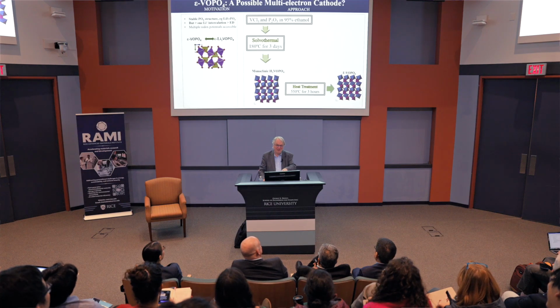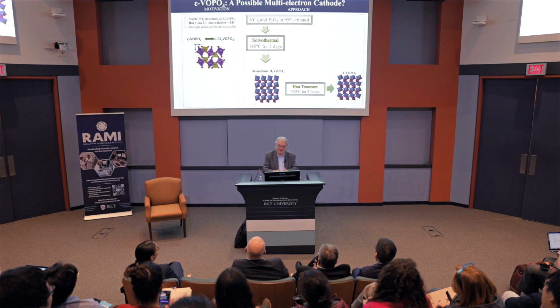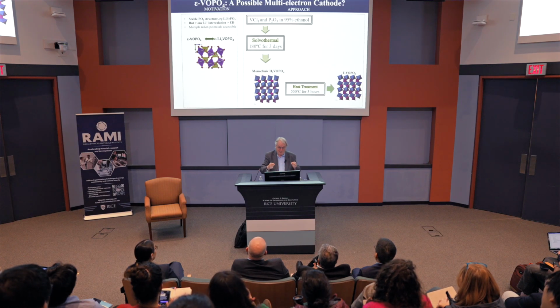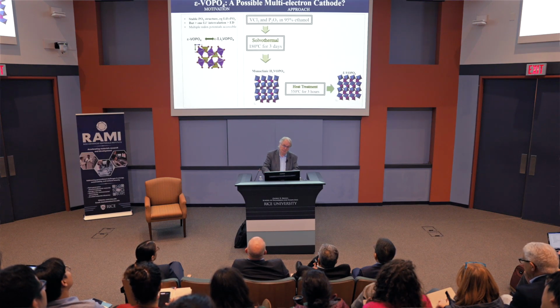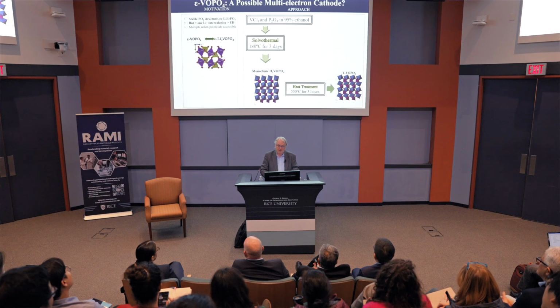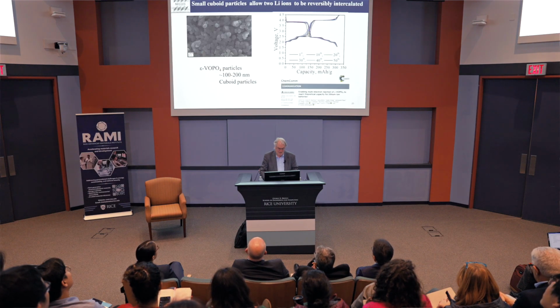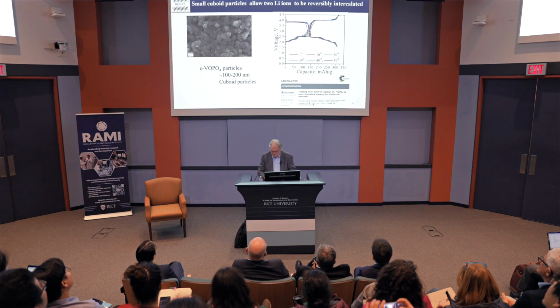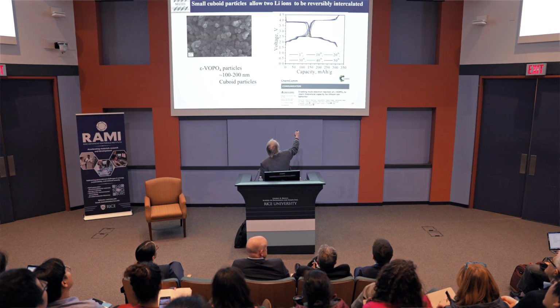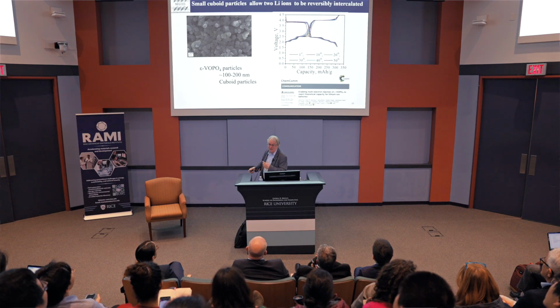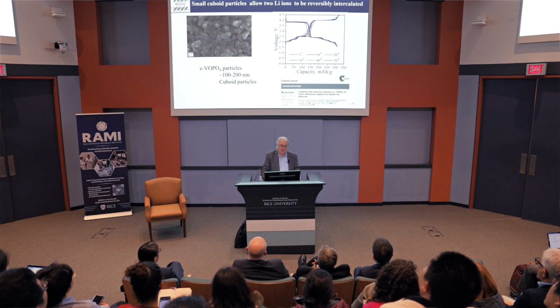We found by other methods we can get this up, but they found out that you make this nice tunnel structure, has protons in it, and then you can heat it to get the protons out, or we show you can, in fact, electrochemically pull the protons out. So you can make this nice three-dimensional lattice with tunnels in all directions so they won't block. These are little cuboids she made on the left-hand side there, and on the right-hand side you can see the discharge curves of vanadium 5 to vanadium 4, vanadium 4 to vanadium 3, and the first cycle is this one here. The 50th one is in the middle. So this behaves better, in fact, on the 50th cycle than the first one. So we had proof of principle.